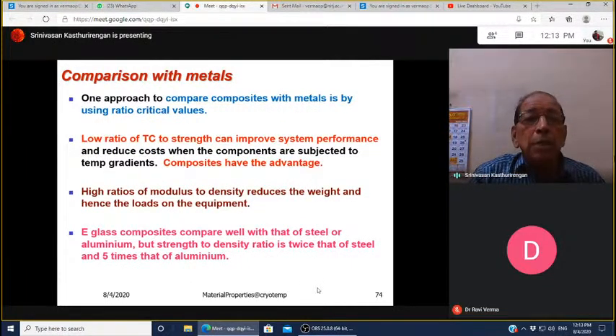How do you compare this with the metals? You can compare it by using ratio critical values. A low ratio of thermal conductivity to strength can improve the system performance and reduce the cost when the composites are subjected to large temperature gradients. So composites certainly have an advantage when you have a large temperature gradient in terms of thermal conductivity. High ratios of modulus to density will reduce the weight and hence the loads on the equipment. For example, E-glass composites compare well with that of steel or aluminum. The strength to density ratio becomes at least twice for steel and almost 5 times for that of aluminum.